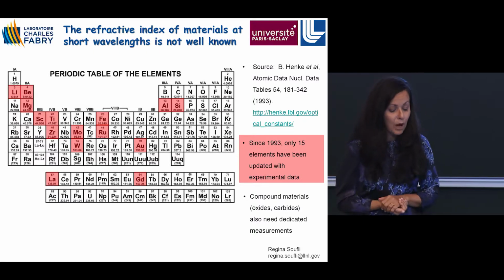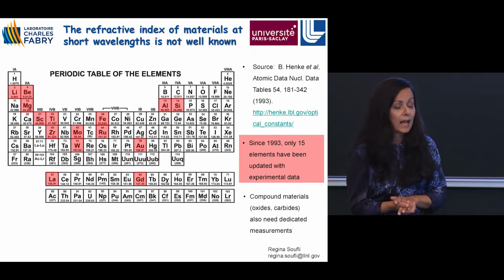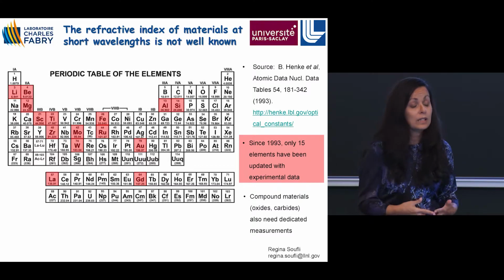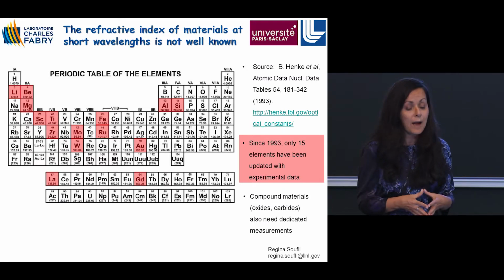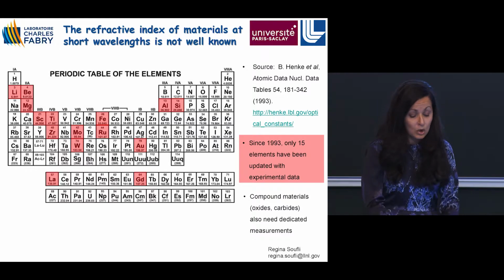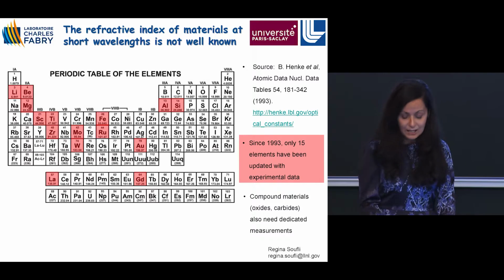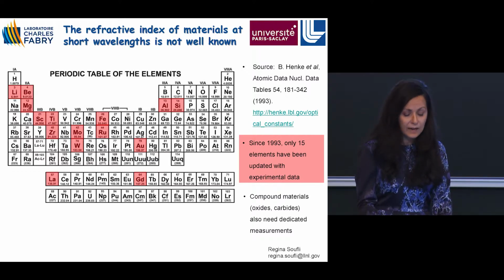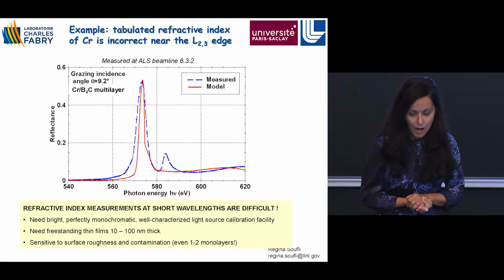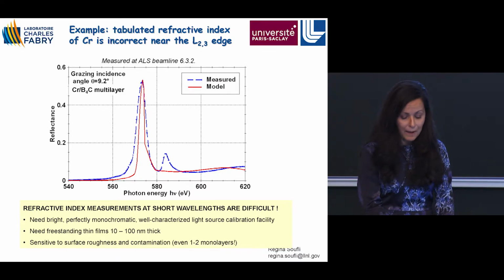And furthermore, for compound materials, these, again, atomic-like approximations are not accurate, and therefore you need dedicated measurements for compounds like the carbides and oxides that we find in these multilayers. So statistically speaking, if you look at this table, chances are the refractive index values you are using are not very accurate. And here is an example. We made a chromium boron carbide multilayer, and we measured it, and we tried to model its performance in the vicinity of the chromium L23 edge. And it turns out that the available values for chromium fail very badly to predict the shape of the multilayer response, and also this peak here, which turns out to belong to the chromium L2 edge.